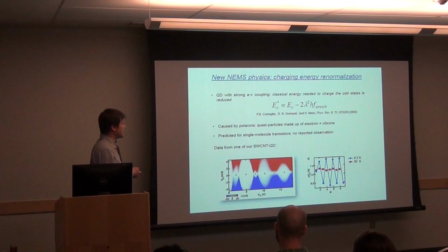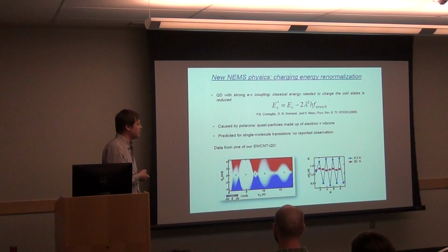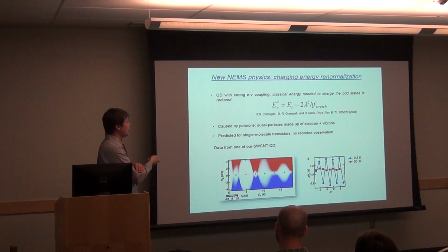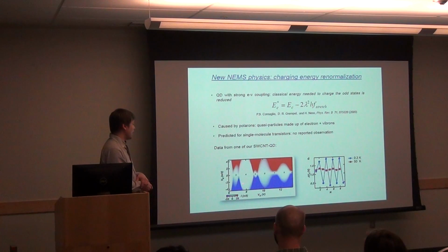There's also new physics that is achievable, for example, in carbon nanotubes. If you have very strong coupling between electrons and vibrons, it's predicted that the charging energy of a quantum dot could be changed so much that the charging energy could basically become negative for some of the states. What that means is that for odd states, odd number of electrons, you could have very small charging energy and very big one for even, and even have it go pretty much to zero for odd states. So this is preliminary data where we think we observe this effect, and it's basically from the coupling between the stretching phonons and the electrons.